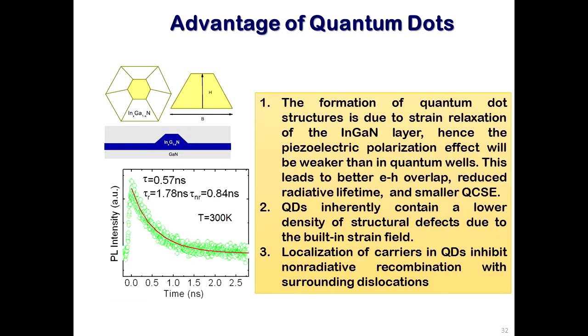and our charter was to try and do things that could not be done with quantum wells. So these quantum dots, if they could be inserted in LEDs or lasers, would obviously have much weaker polarization fields, and therefore smaller blue shifts. And with the localization of carriers in these three-dimensional quantum dots, the carriers would not wander away as they do in quantum wells and recombine in non-radiative centers. They would stay confined and recombine radiatively and give out light. So that was the premise.